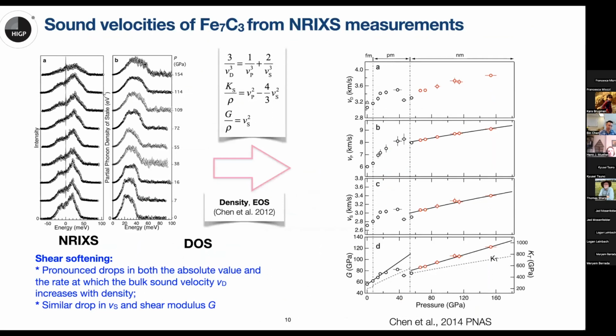The NRIXS data could give us the Debye sound velocity. We have previously determined the equation of state of the Fe7C3 phase. Now, using these three equations with three variables, we can calculate both the compressional wave velocity and the shear wave velocity. From our experimental data, we can see a pronounced drop in both absolute value and the rate at which the bulk sound velocity increases with density. And there's a similar drop also in Vs, the shear wave velocity, and the shear modulus.